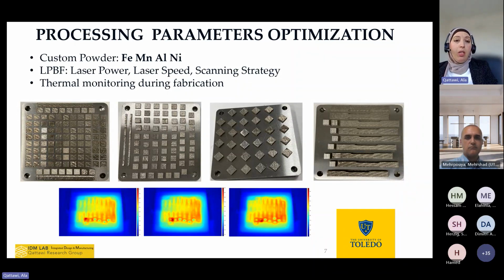And in some research, other than the iron shape memory alloy, for superalloys like nickel, this has proven to even heat treat the part or the material while we are printing. So we're actually reducing the number of steps we have to do in order to produce the part. And all of these conclusions came through in-situ thermal monitoring of the production of the metal. You can see on the left, we started with a very wide window, because we need to optimize these process parameters until we reached a point, with thermal monitoring and understanding of the defects that each window yields, where we have a viable material that we can actually test, with acceptable porosity and an acceptable density that we need.